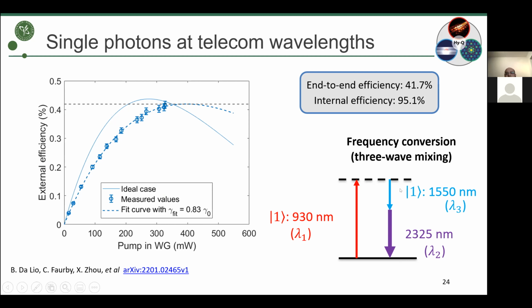Now, unfortunately, it's not easy to do this, but you can do it with a nonlinear process called three-wave mixing. What you have to do is basically provide the missing energy of the photons through an external pump. So you get a laser that works at this very particular wavelength, 2325. You mix it together with this photon, and what comes out is photons at telecommunication wavelength. You need a particular material which has a particular nonlinear coefficient. It's called lithium niobate. But actually, it works extremely well. We got very high conversion efficiency, so 42% of the photons get converted to 1550, and I think it can be improved further.